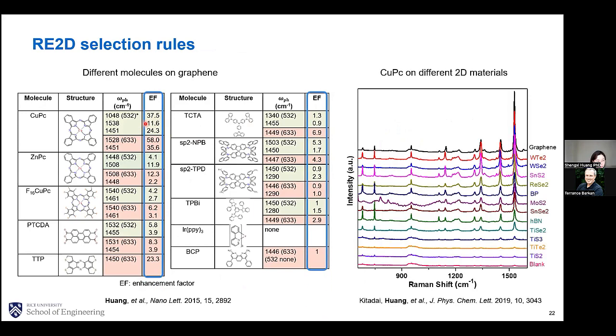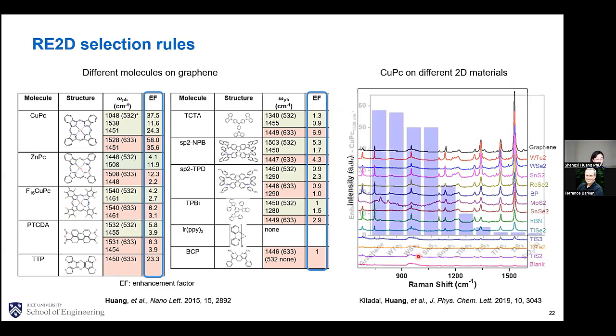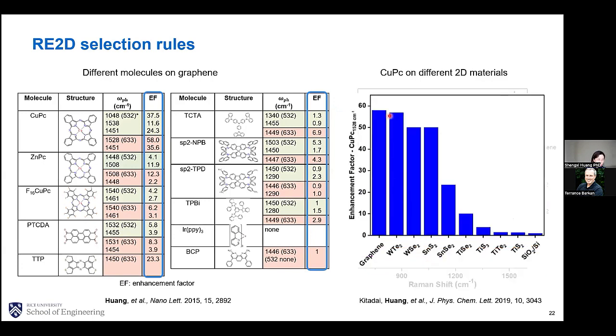On the other hand, if you just put one molecule, for example, CuPC, but you put it on different 2D materials, you can also see the Raman enhancement factors can be very different from each other, as you can see in these Raman spectra. And actually, if I summarize the enhancement factor for one of the CuPC Raman modes, you can see the enhancement factors are indeed very different.